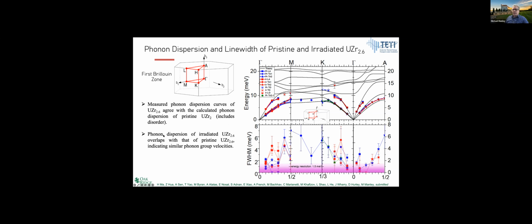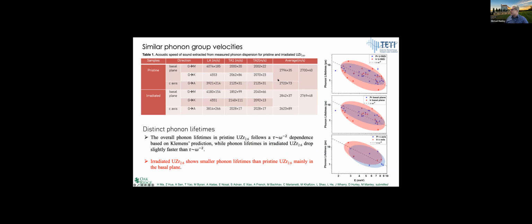particularly at the zone edges. You can also look at group velocities, and basically from looking at the dispersion, they're not changing much. To within error, they're basically the same group velocities. But the lifetimes get more spread out with irradiation. Some of them get a lot shorter. The top one is basically all the lifetimes. It's not shown what's what there, and it's plotted versus 1 over energy squared in a log plot to give you an idea. That's sort of regular phonon scattering behavior, but it has all these other kinds of contributions, and the spread grows with irradiation. So there's a suppression of some, but this also occurs. The bigger effects are in the basal plane, less so along the c-axis, and that turns out to be consistent with what we see in the thermal conductivity, which I'll talk about in a minute.